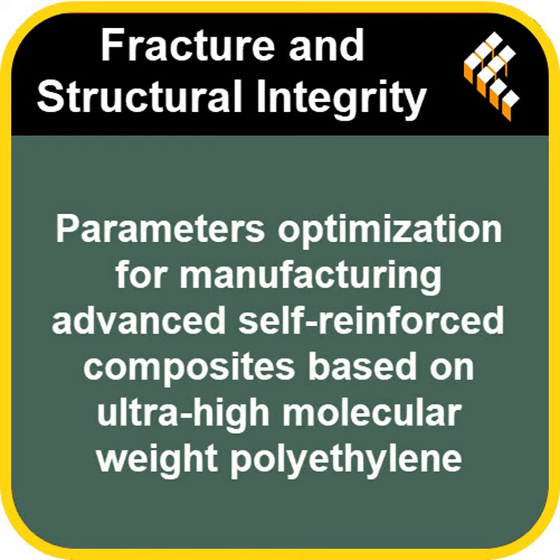And did the pressure they used during manufacturing make a difference here? They tested 25 and 50 MPa, right? It did make a difference, but maybe not how you'd expect. The higher pressure, 50 MPa, didn't really change the maximum strength or stiffness they could achieve. Those peak values stayed about the same. So what did the higher pressure do? It shifted the temperature at which those peaks occurred. With higher pressure, you needed a slightly higher temperature to get the best results.